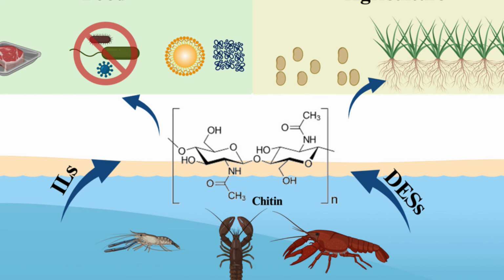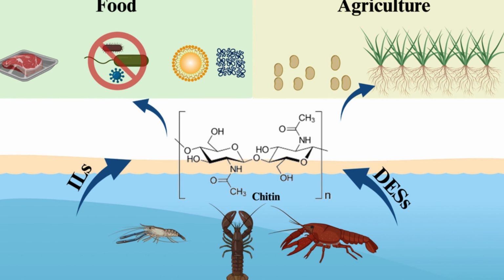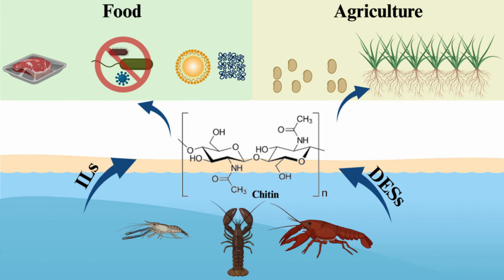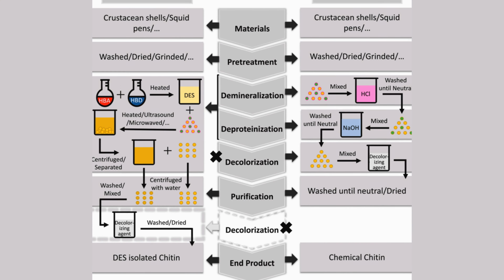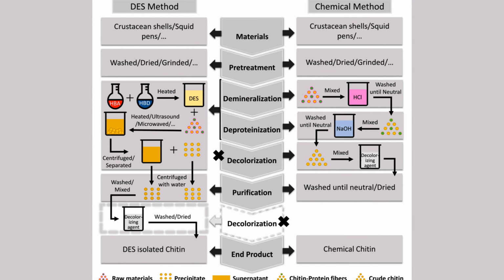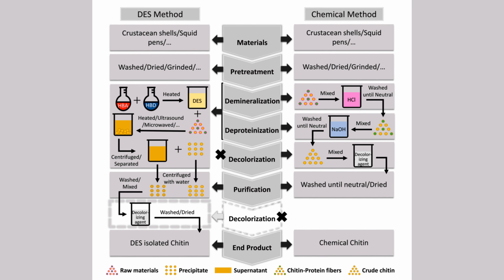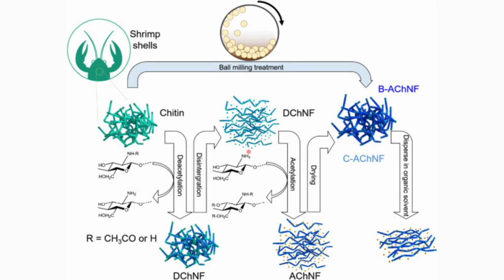Multiple 2024 to 2025 reviews and case studies show DES, for example choline chloride-based, can delaminate and deproteinize insect and crustacean shells at lower temperatures and be recycled, improving E factors versus mineral acids and alkali. Fungal and insect chitin is especially DES amenable and avoids seafood allergens. Mechanochemistry. Solvent-free ball milling routes can cross-link or functionalize chitosan, e.g. with polyanions, and directly yield robust sorbents, useful for water treatment without wet chemistry.